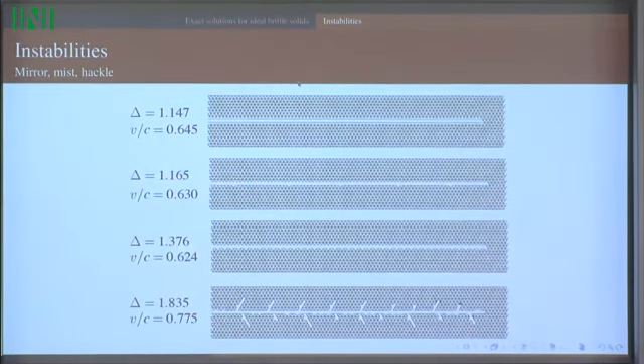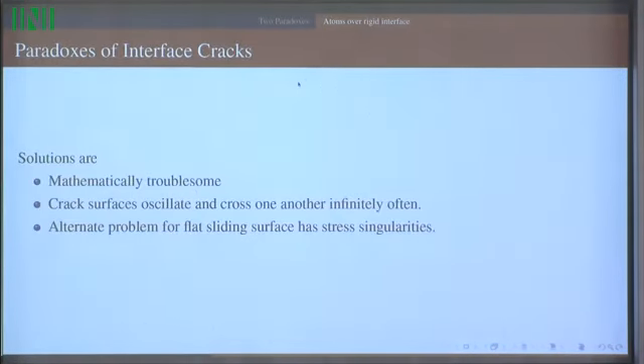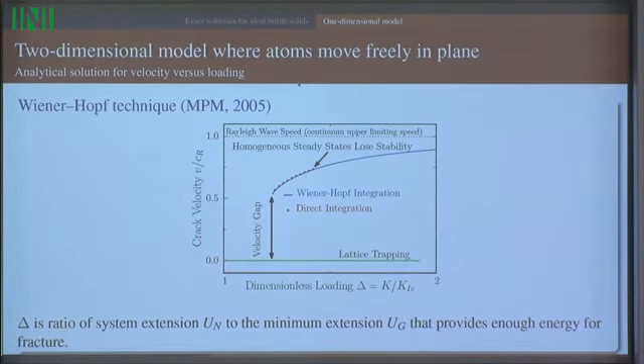And so this is something perfectly accessible within a Wiener-Hopf framework. I show here a sequence from a numerical sequence where I solved the thing, and you can actually see an instability emerging, which forms branching-like structures. But if I come back here, that's the point where the Wiener-Hopf technique says that steady states lose stability towards horizontal bonds breaking, and therefore the steady state assumption that we've been making about the dance of atoms is out the window. It can start to form branches, and this moves beyond the level at which I at least was ever able to solve anything analytically, but at least you can identify the origin of the instability in an analytical solution.